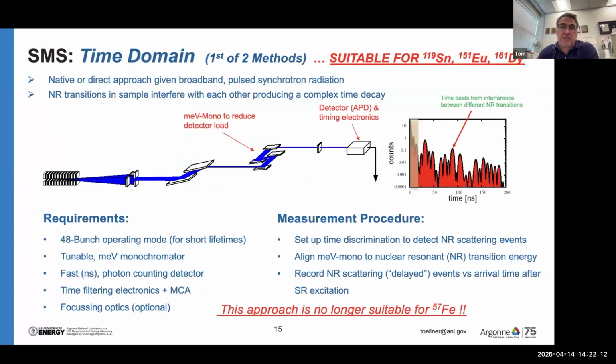So the time domain approach, the setup looks very similar to the vibrational spectroscopy. The only difference is the meV monochromator is left stationary. We do not scan the incident energy. We simply go to the nuclear transition energy and the mono sits there. And then we do time differential detection of the X-rays that come off the sample. The detector has to be placed further from the sample to avoid any incoherent nuclear resonance scattering, so that you just get the forward scattering signal. This requires 48 bunch mode, and this will be the approach that we use for tin, europium, and dysprosium.